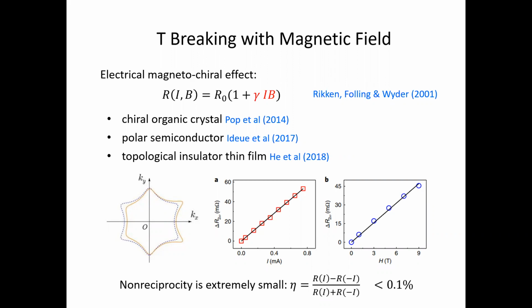However, this degree of non-reciprocity, which is quantified by this dimensionless number, the difference of the resistance at forward and backward current divided by the average, is extremely small. It's less than one part per 1,000, something like that. And this is perhaps not surprising because, in the case of, for example, topological insulator surface states, the magnetic field couples to the electron spin, and there's a strong spin orbit coupling. Therefore, applying a magnetic field leads to a distortion of the electron energy momentum relation.